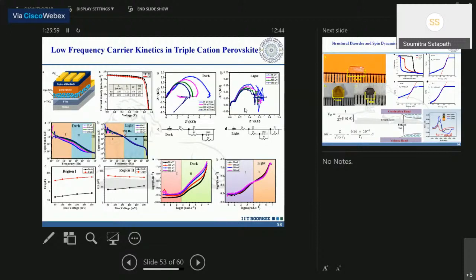But this goes away when you put on the light. And if you look at region 1, region 2 and region 3, they are the three defined frequency regions. One is the low frequency region, another is the intermediate frequency region, another is the high frequency region. So the behavior of the capacitance versus frequency graph is different as you change the bias from 50 millivolt to 200 millivolt. At low frequency, you see that with the bias it is increasing. That is quite expected. These three different frequency regions are dominated by three different kinds of capacitors. Region 1, the low frequency region, is dominated by the carrier or storage capacitance. Region 3, the high frequency region, is the geometric capacitance, and region 2 is the internal capacitance.